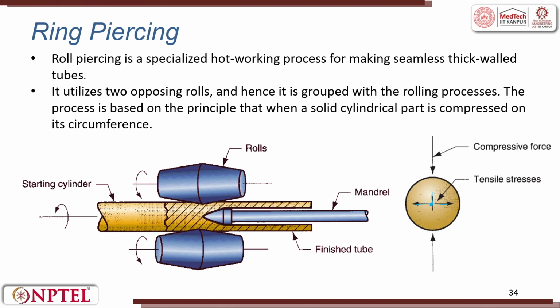So, here there will be a crack which is formed and you will try to have a hollow shape. So, the rolling piercing is a specialized hot working process for making seamless thick wall tubes. Seamless tubes are tubes where there is no seam. If you take an ordinary sheet and roll it, you will have something like this, right. And then finally, what you do is you try to weld it.